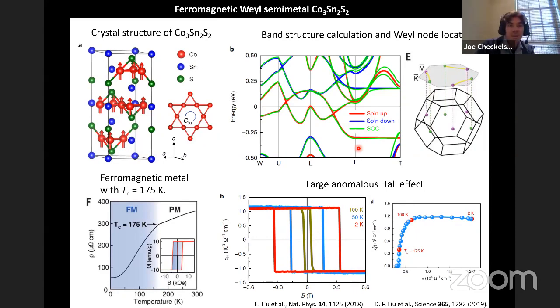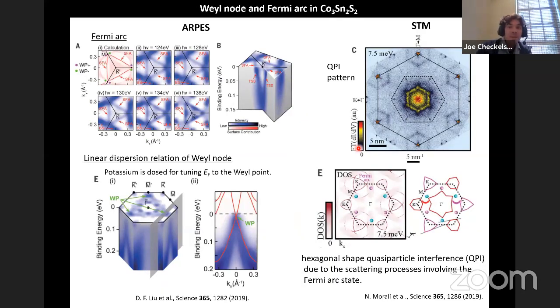In terms of spectroscopy, these were very challenging experiments, but were recently done. For example, this is a combination of a calculation and then photoemission. These sorts of Fermi arcs that were expected to be seen on the surface were observed. And then these Weyl points, I think aided by some surface doping of potassium, you could also see these kinds of linearly dispersing Weyl points. So it's really just a demonstration that indeed magnetism can drive this kind of Weyl electronic structure. And for completeness, I would mention there were also beautiful experiments done by STM, which showed through quasiparticle interference that you could also see these things.